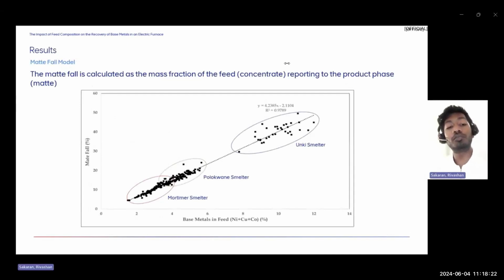In addition to those data-driven models, the matte fall calculation was also shown, and the Mortimer smelter, Polokwane smelter, and Unki smelter ultimately fall on the same line. What's interesting to note, though, is that the Unki smelter does have some variation, but this was due to some of the calculations that were done. When the amount of matte is calculated, it is assumed that there is a constant silica content in the matte when it's poured into the silica sand beds. In addition to this, there was an assumption that the lime that was added into the concentrate was always consistent and had a constant concentration the entire time.